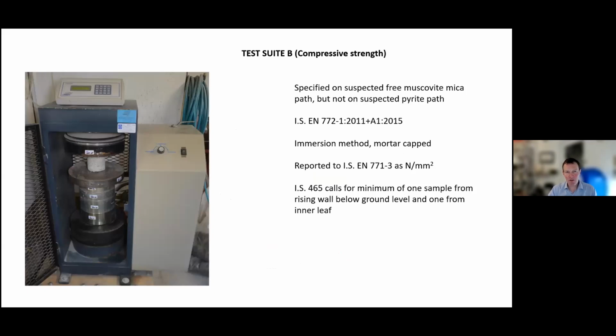Test suite B also includes compressive strength in the muscovite mica path, but not on the suspected pyrite path. And this may be an oversight and may need to be revised in time. This is a standard method. Engineers will be most familiar with it, where effectively you compress the concrete until it fails and you record the force that's required to compress it. So IS465 calls for a minimum of one sample from the rising wall and one sample from the inner leaf